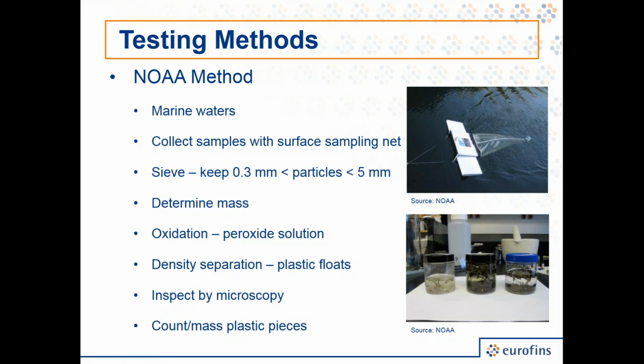Then the solution that results goes through a density adjustment so that you can make the plastic particles float. You can collect those, and then once you have the plastic particles collected, you can perform microscopy and then go forward with either a count on the number of particles you found or determining mass. So the two methods are related in that in the end you're isolating plastic particles that you're going to characterize, but they focus on slightly different matrices.